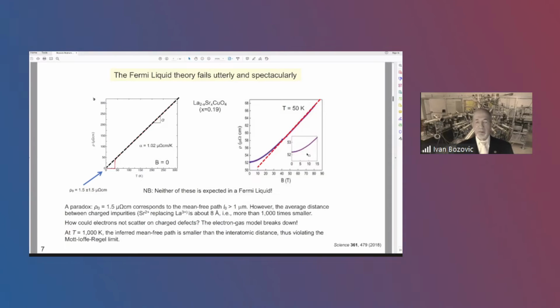And the mean free path that you would infer even from the upper limit on this residual resistivity would be like 1,000 times longer. So what we infer is that at low temperatures, the electrons do not scatter on anything, while at high temperature, they scatter on nothing, on vacuum. And this, of course, is absurd. The only sensible conclusion is that the standard Fermi liquid theory fails spectacularly.